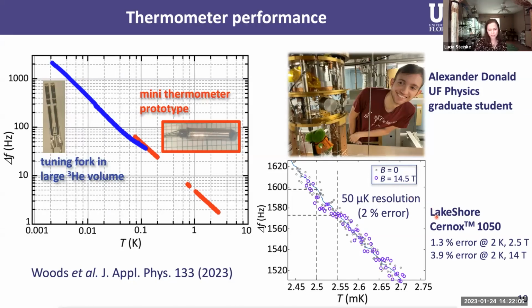And if I compare that to commercially available resistor thermometers, which might do this job at higher temperature, it's comparable if we are at low field. But if we apply a sizable magnetic field, like 14 Tesla, the resolution of my thermometer stays the same and this one doubles. So my thermometers actually also work better in magnetic fields. So this is really all I wanted from them. I now hope that we can put these to use in user experiments in the future.